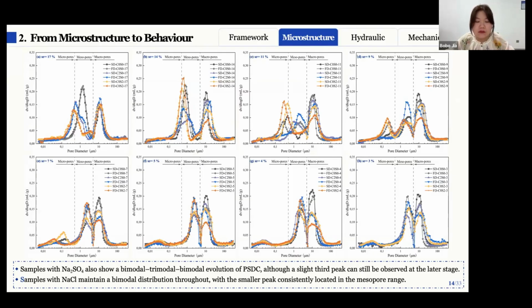So regarding the effects of the salt type, sodium chloride is C2 and C3, and sodium sulfate is S2 and S3. These figures show the PSD curves at different water contents. The black and gray values correspond to the C0 S0 samples under fast and slow drying, the blue and the green represent C2, and the orange and the yellow are S2. For the sodium sulfate S2 samples, the PSD still follows a bimodal model, then a trimodal model, and then back to a bimodal pattern. But a weak third peak remains at the last stage. This may be related to the strong water film seeking effect of sodium sulfate, and as a result, the trimodal structure persists for a long time.